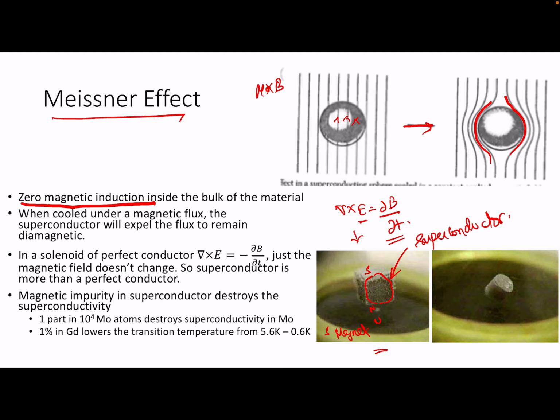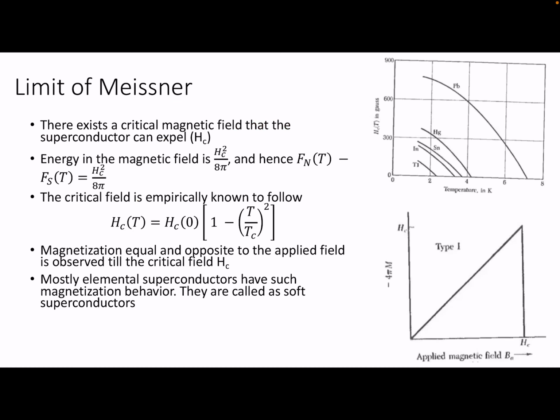Whenever you add magnetic impurity to a superconductor, it destroys the superconductivity. Something as small as 1 in 10 to the power 4 iron atoms in molybdenum destroys the superconductivity in molybdenum. 1% gadolinium will lower the transition temperature from 5.6 to 0.6 Kelvin. So there is a strong effect of magnetic material inside a superconductor.